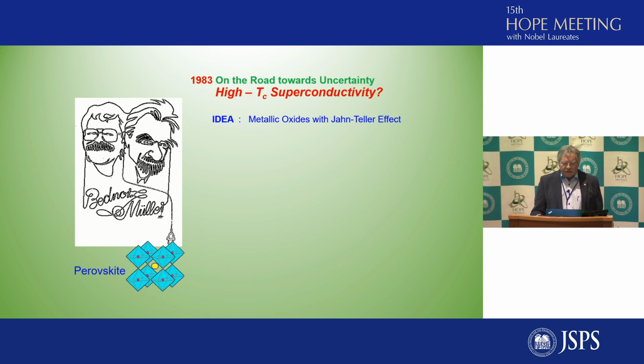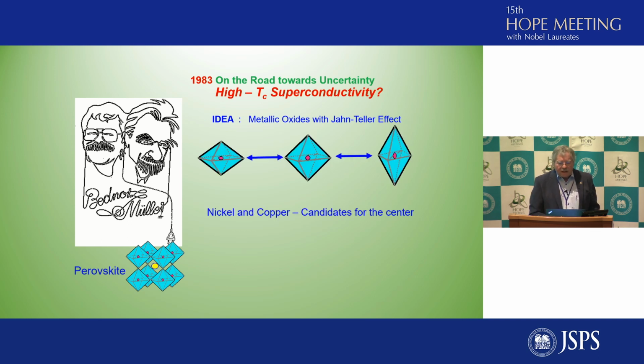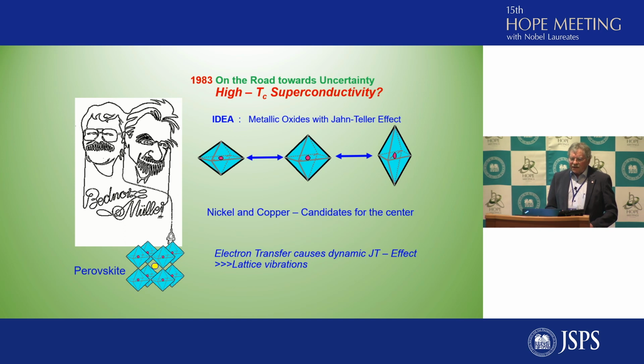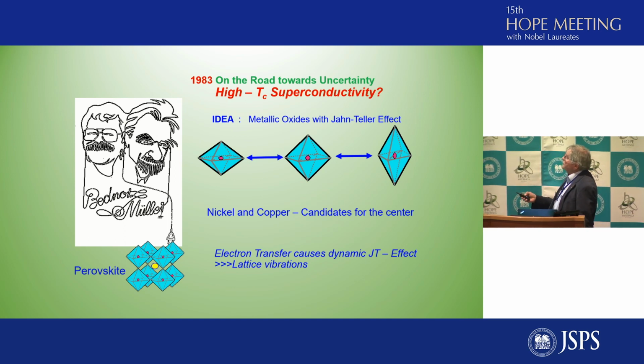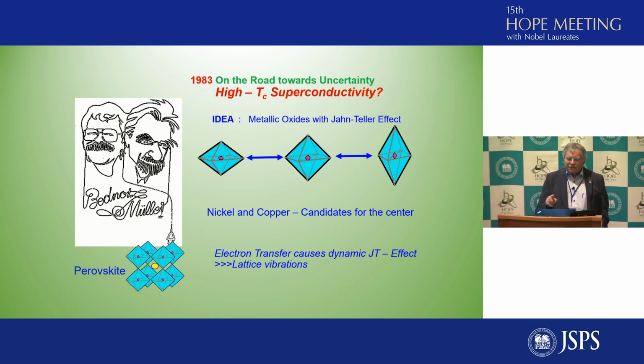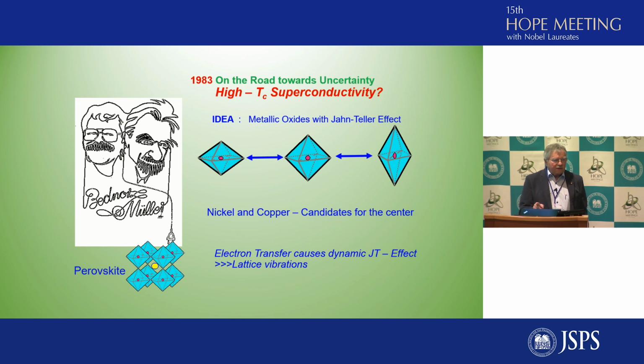The Jahn-Teller effect means that the octahedra is reacting when, for instance, nickel or copper in the center would adopt a trivalent or divalent state. So in one case, it could stretch. In the other case, it could contract from the original symmetric way. And if this would be a dynamic effect in a conducting material, it could create polarons.